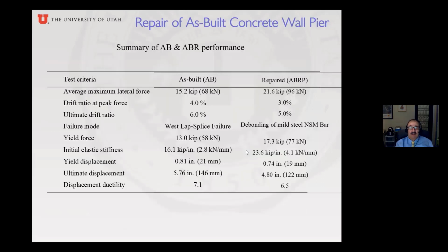And if we compare the numbers, we went from 15 kips for the as-built to 22 for the repair. The drift ratio at the peak was 4%. We went down a little bit, 3%. Ultimate was 6. We went down to 5. The failure mode of the original was the lap splice failure. And as far as the repair, we debonded the mild steel bars.